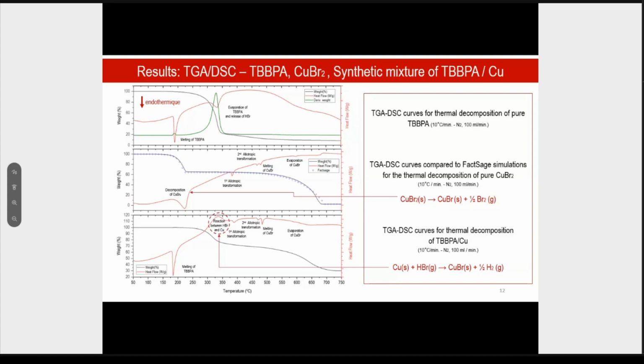Then finally, we compare the signals for a synthetic mixture of tetrabromobisphenol A with copper to the behavior of the pure copper bromide and the pure flame retardant TBBPA. By comparing the third signal with the first two, you can see that by mixing tetrabromobisphenol A with copper, the system always starts by melting the tetrabromobisphenol A, followed by an exothermic reaction between the hydrogen bromide released and the copper metal. Then it follows the same behavior as copper bromide: two allotropic transformations, then melting and evaporation of copper bromide.